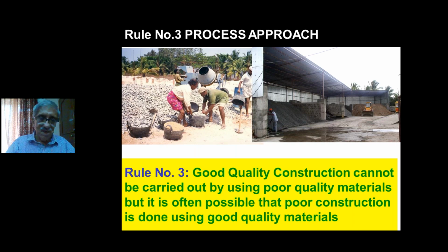On the right hand side, you see the scenario of a ready mix plant in Nasik, where proper quality control was established by the person in charge, and he has made partitions of the correct size where separately different graded particles are stacked, especially the aggregates, etc. And also care was taken to spray some water during the hot weather, so that when the water evaporates, it cools the aggregate, and therefore in the batching plant you get a lower temperature concrete initially, which is good, because otherwise the cement will start setting and consuming the water, and the mix will become stiffer much faster than required. So all these processes are very, very important.